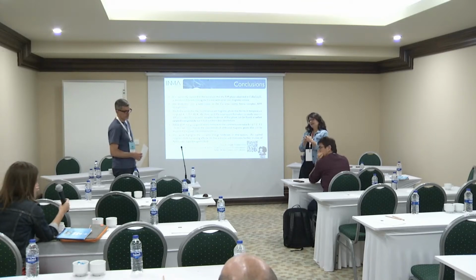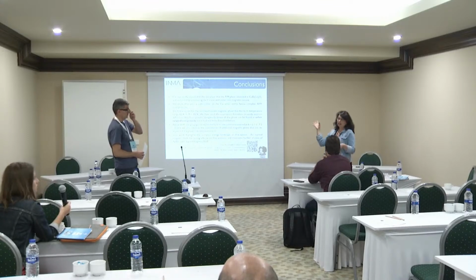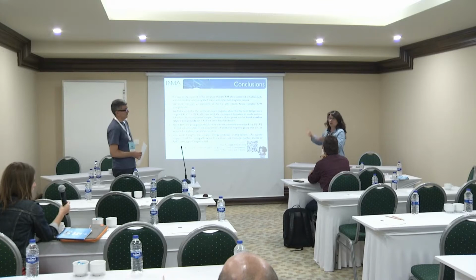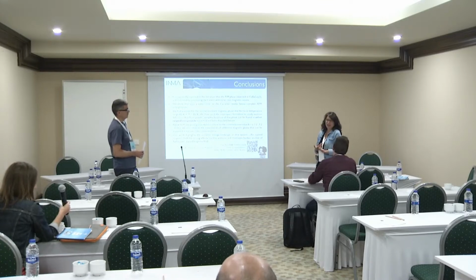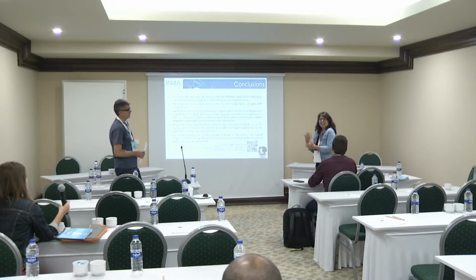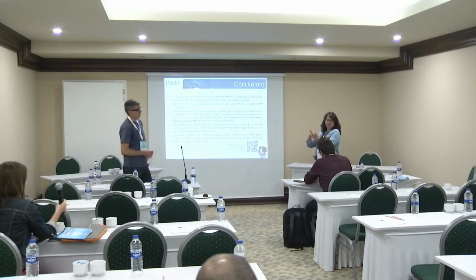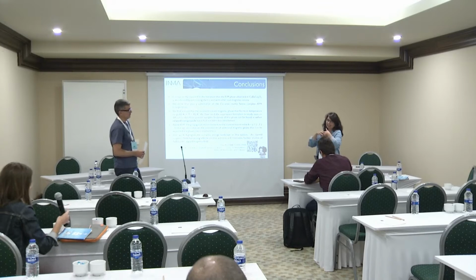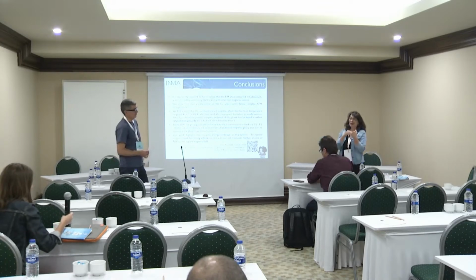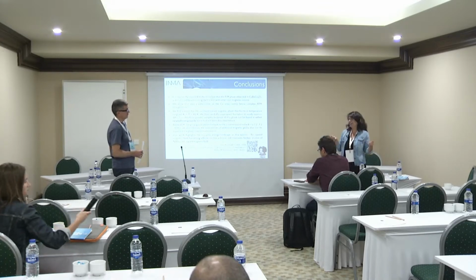But beyond that, there is no strong effect on what kind of magnetic structure you expect, or how it will evolve? No, not that we have found, and as soon as these other phases start to emerge, the increase in polarization is not so big. So it doesn't go in the direction that we would like, let's say, for applications, but I think it contributes to our understanding of the stability of the system.